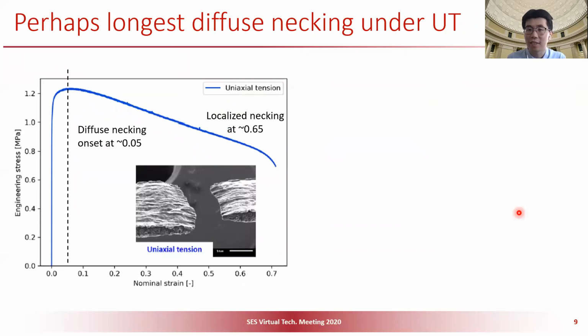Okay, and for the third difficulty, actually, today is my focus of our test results. See here, this is the nominal stress strain curve, or the engineering stress strain curve, of uniaxial tension. We can see that this is really interesting. There is a clear peak force or peak engineering stress. So that means there is necking. Before necking, this range is really short, about 0.05. Between 0.05 and all the way to 0.65, this is a very long stage of diffuse necking. And after that, there is localized necking.